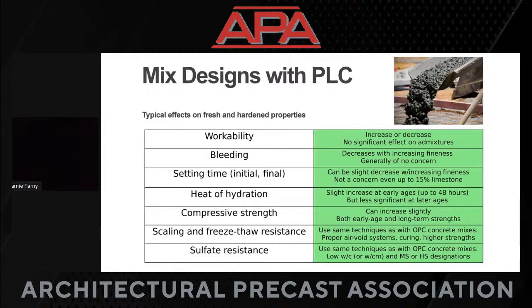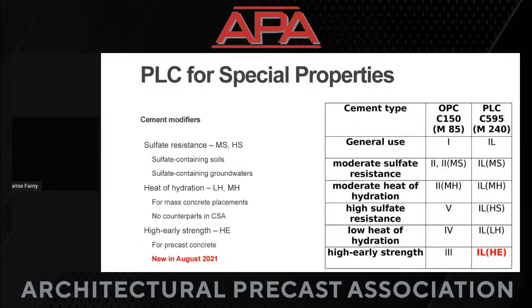But the message for all of those durability issues is that whatever you're doing for your ordinary Portland cement mixes, whether it's a proper air void system through admixtures, or good curing, or turning to higher strength, or using an SCM as part of your mix, whatever you do for your ordinary Portland cement mixes, you do the same thing. You take the same approach with the PLC, and then you test and you confirm: is it a good performance?